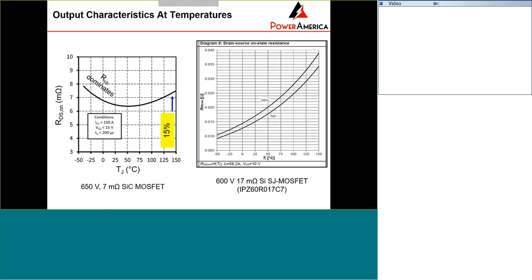We compare this resistance dependent on the temperature with the 600 volt 17 milliohm silicon superjunction MOSFET, as shown in the right figure. You will see that for the silicon superjunction MOSFET, the temperature coefficient is very positive, and it increased twice at 150 degrees C compared to room temperature. And we also plot the silicon carbide MOSFET curve to compare with the silicon. You can see that this silicon carbide device is pretty flat over the temperature.